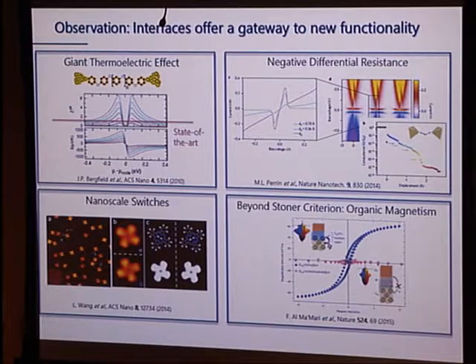And one that has generated quite a bit of wave, we'll have to see if it really holds up, is that there seems to be a potential to get magnetic materials that are based on organic interfaces, meaning organics with other materials, that go beyond the Stoner criterion. The Stoner criterion says that you should have a ferromagnet only if you have a certain product of the density of states and the exchange coupling strength. So here it seems that we beat that limit if the data can be believed and if the interpretation is as suggested, and we can have new types of magnetic materials.